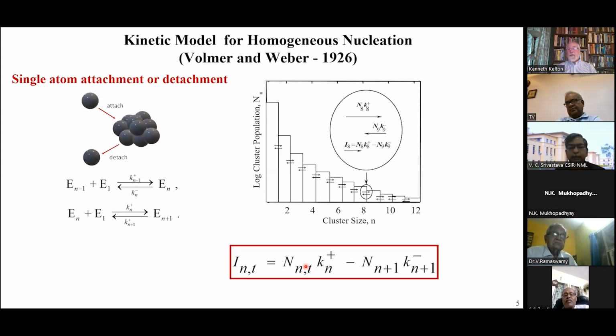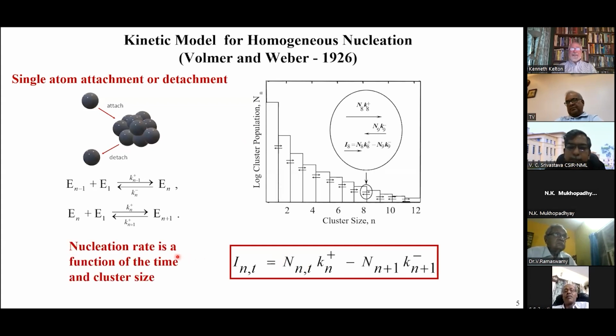And that's just given by this. This is an important point. It points out that the nucleation rate is in general a function of time and a function of the cluster size at which you measure it. These are all considerations we typically don't think about, but they are important, as I'll show you later.